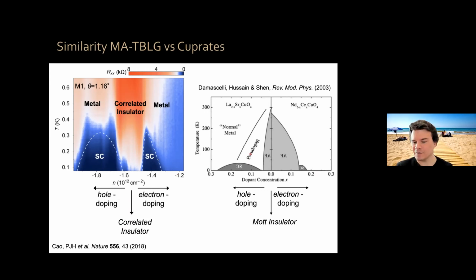Now, a big difference between these is that this is a theoretical phase diagram. In order to populate this with experimental points, you have to grow hundreds of crystals with different doping, often with different material classes, because not all crystals can be grown for electron doping and for hole doping, whereas this is all realized in a single device, in a single cool down, with a single disordered realization, and where I can tune electrically from here to here in a few seconds. So that's something that obviously attracted a lot of attention.